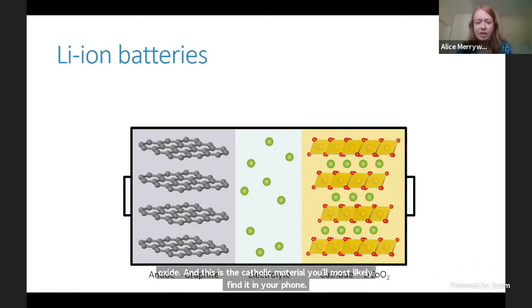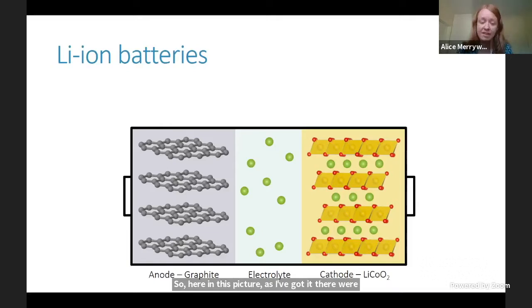So here in this picture, as I've got it there, we're looking at the battery in its discharged state. No lithium inside the graphite anode, but there are some lithium ions already stored inside the cathode material. So this lithium cobalt oxide has got this lovely layered structure, these alternating layers of cobalt ions that I've shown in the green. And this layered structure is really important because it means that the lithium ions can slot in and out of those gaps between the cobalt layers and come in and out of the material.